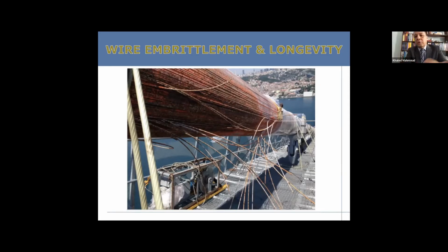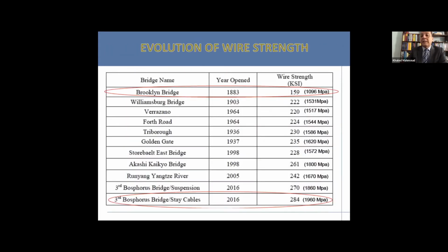Of course, we fix all these wires, we splice them, and we provide tension back in them, and we move forward. But the issue is, if you have too many of these, and if you have cracked wires that are yet to break, that will of course impact the longevity and will reduce the service life. All these broken wires had brittle fractures, and they had no cross-sectional loss, and emphasis was placed on the brittleness of those fractures.